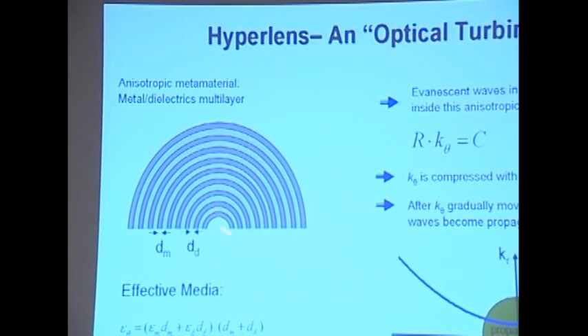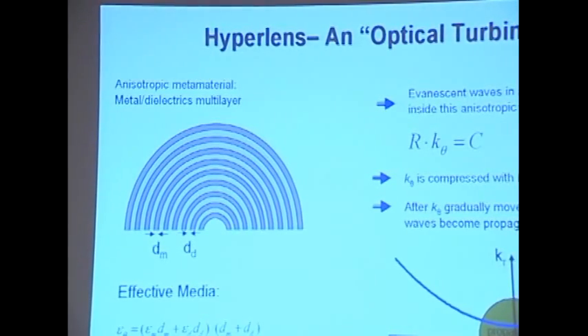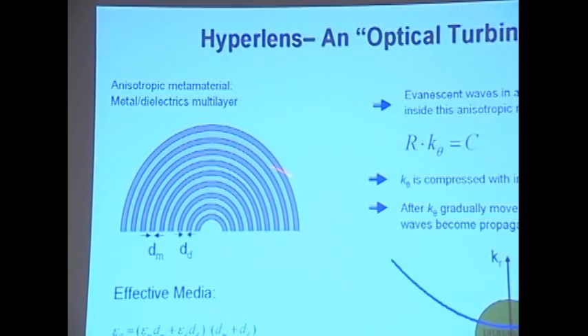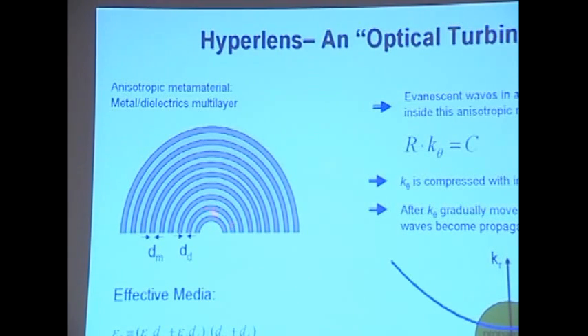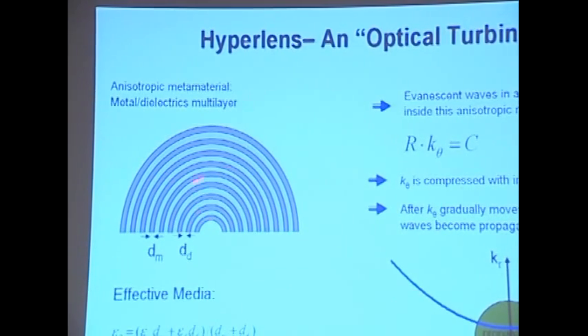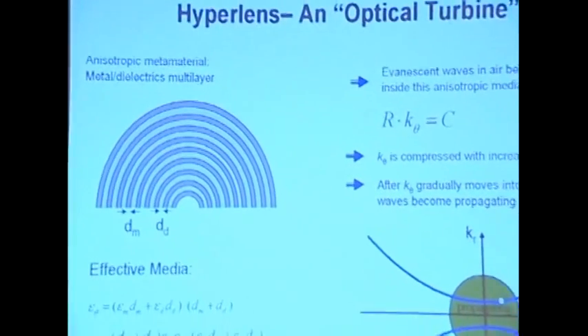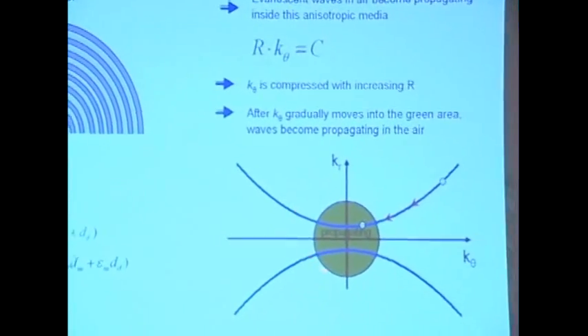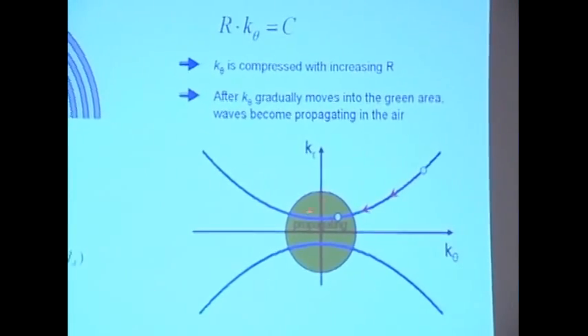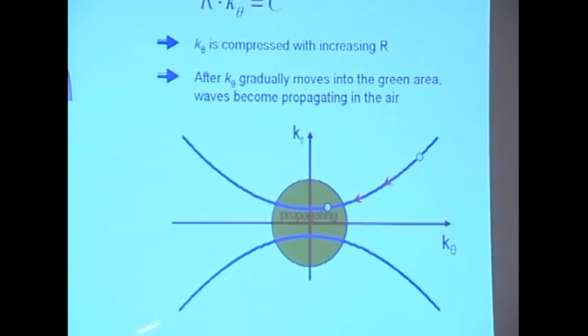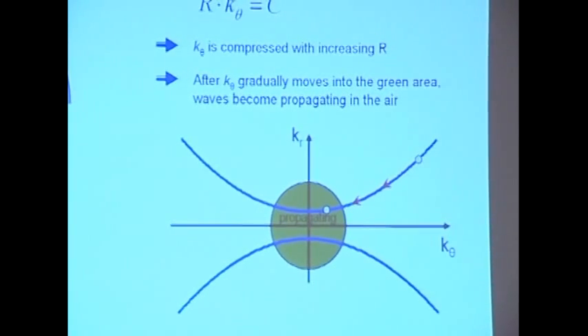Essentially, this is a multi-layer metal-dielectric system, and everything is sub-wavelength, okay? These layers are about 30 nanometers each. And you carefully design this such that the dispersion is no longer a circle or an ellipse, as we see in regular optics, but rather is hyperbolic.